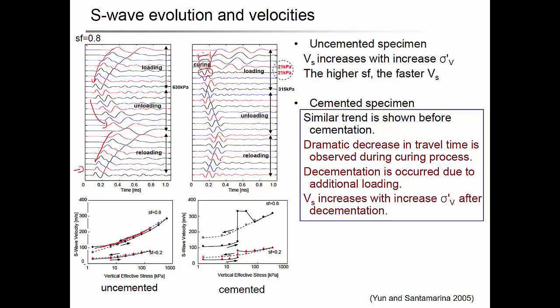And during loading and unloading, here, because of cementation, you have a jump in the wave velocity, and during loading, you have a break of the cement, or the failure. So that it follows this curve, and then the unloading curve is like this. And this shows the decementation by additional loading. Decementation occurred due to additional loading.